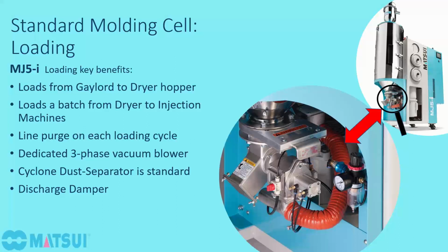So there's never any material remaining in the material line or in the vacuum box after each conveying cycle. When you dry material in your drying hopper, you want to limit the amount of exposure that it has after it leaves the drying hopper to the injection machine. You want to use that material as quickly as you can, especially if it's a very moisture sensitive material like PET or nylon, which can reabsorb moisture fairly quickly. So the discharge damper enables a prescribed amount of material to be conveyed to the injection machine with each conveying cycle. All the material, the complete conveyance of the resin, will go to the injection machine. So that does a very good job at reducing the amount of time the material is exposed after it leaves the drying hopper.